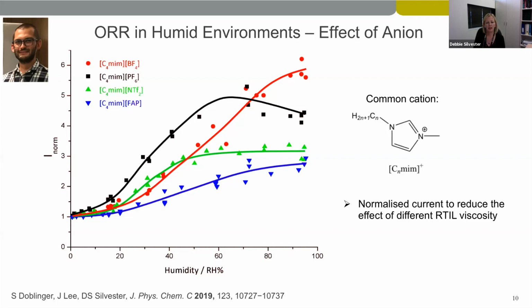What you can see here is when we keep the cation constant, with a C4 MIM cation, and we change the anion, you can see different responses as you go to higher humidity levels. If you look at the highest humidity level, about 95%, some of the ionic liquids, particularly the BF4, have about 6 times the current response compared to the dry environment. The order, BF4, PF6, NTF2 and FAP, follows well with the bulk solubility of water in the ionic liquids. But what's interesting is that in the low humidity range, 0 to 20%, there's not really much of an effect of the different ionic liquids. So it's mainly at the higher humidities where we see the anion effect.